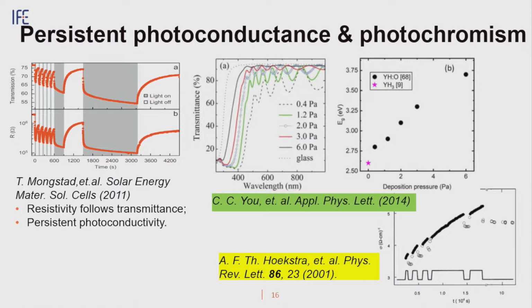How to clarify it? Since the mechanism of persistent photoconductance is very well studied in the physics of semiconductors, I wanted to first study persistent photoconductance, the mechanism of it. And we can learn something by tuning the concentration of anion vacancy. Then I thought, let's tune the hydrogen deposition pressure. In this way, we will control the hydride anion vacancy concentration. Then we should see some difference.